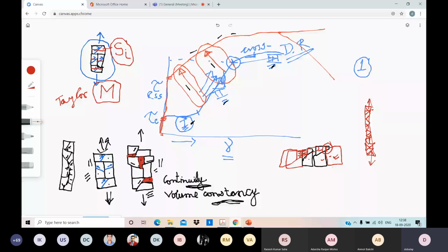For example, if you are working with an anisotropic system like HCP, and you are pulling a specimen like this, and HCP crystals are lying like this, preferably most of them like this, deformation will be very difficult because their basal planes are not getting the necessary resolved shear stress to overcome the critical resolved shear stress. Very interesting, right?